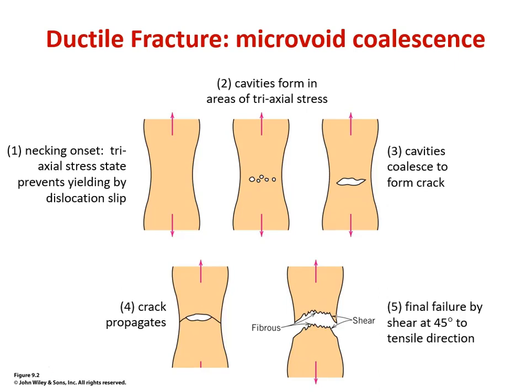This could be a nice ductile thermoplastic maybe, but more likely, given the steps we'll go through, this is going to be a metal, something like low carbon steel or copper or aluminum. So we're again going to think in terms of a round tensile bar, pulling on this in our uniaxial tensile tester. The first thing we'll have is some elastic extension, then some uniform plastic deformation, and then we're going to get up to the point of ultimate tensile stress, where we'll start to have that localized plastic deformation that we described as necking.